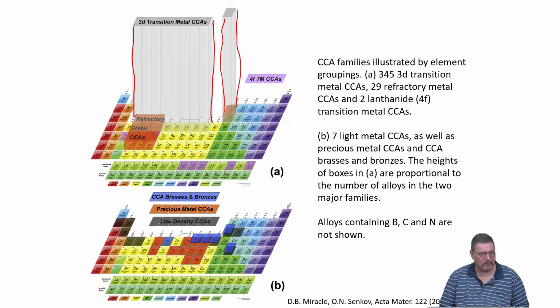And this mixing enthalpy as well as the difference in effective atomic radii in solution are the two most important, I think. So the similarities in these properties between the different atoms and different atom pairs control whether you can easily make a solid solution or whether you will probably find formation of an intermetallic phase, which most of the time is to be avoided.